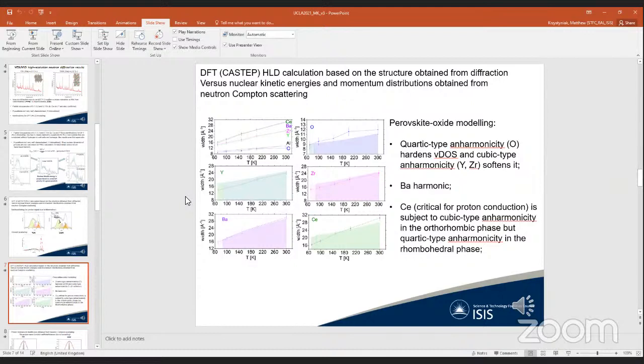And we know from the theory that whenever we see a result from experiment which is actually showing overbinding, so higher width of momentum distribution compared to lattice dynamics prediction, we have quartic type anharmonicity. Whenever you see something which is softening of the mode, so smaller kinetic energy, we have cubic type of anharmonicity. So we can characterize the anharmonicities of all those local binding potentials of all metals and oxygen present in the perovskite oxide lattice by using Compton scattering.